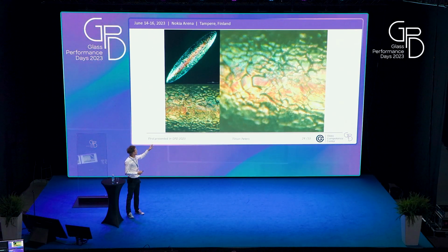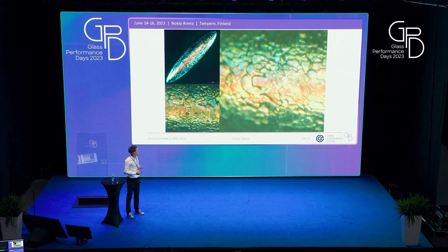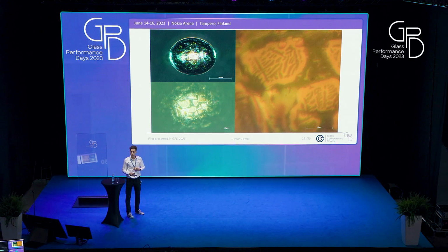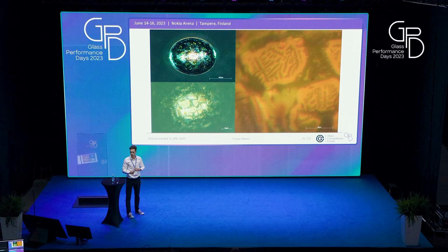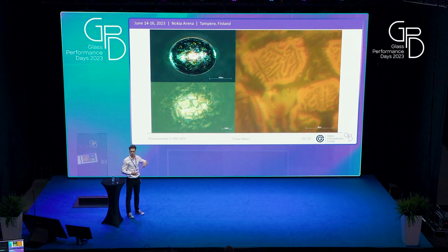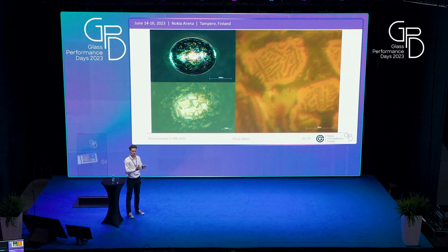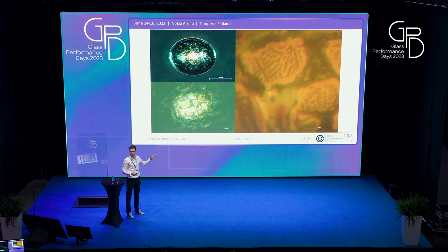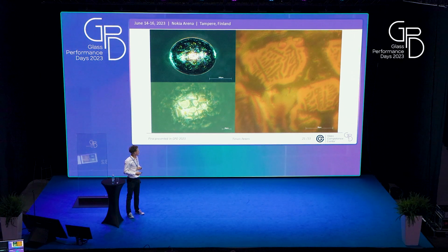You can see the crystal lattice on the surface of these crystallites. Here you can see it even better under very high resolution. And this photo was taken through the intact glass, so you could theoretically assess your glass if you just look closely enough and directly determine that this is nickel sulfide because of this characteristic crystal lattice structure.